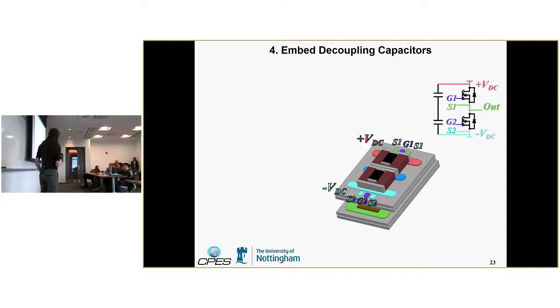Okay, then by having this top insulating substrate, we can also have a higher level of integration. So we're also embedding decoupling capacitors. What that does is it gives a very low impedance, high frequency power loop path. So we get a power loop inductance of about 4 nanohenry. And the gate loop inductance is also small, around 3.8 nanohenry.